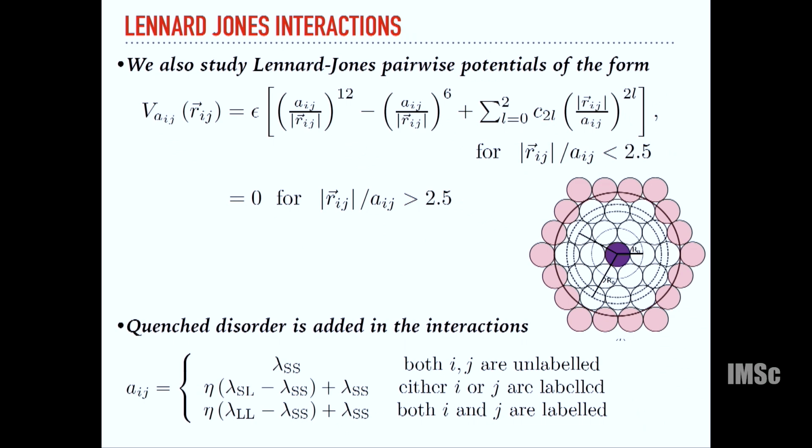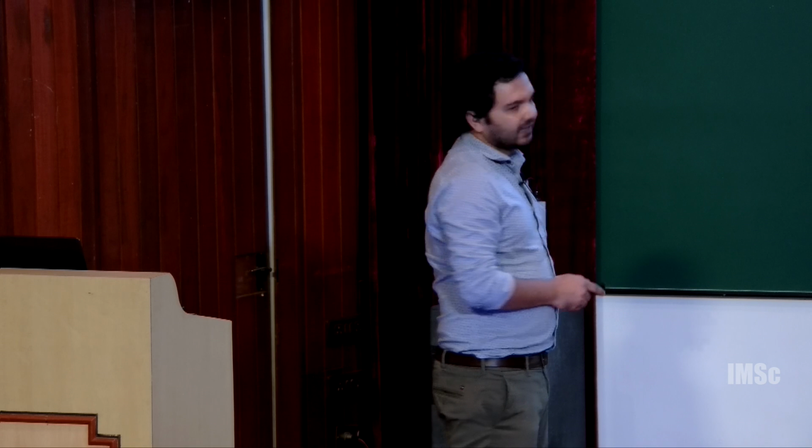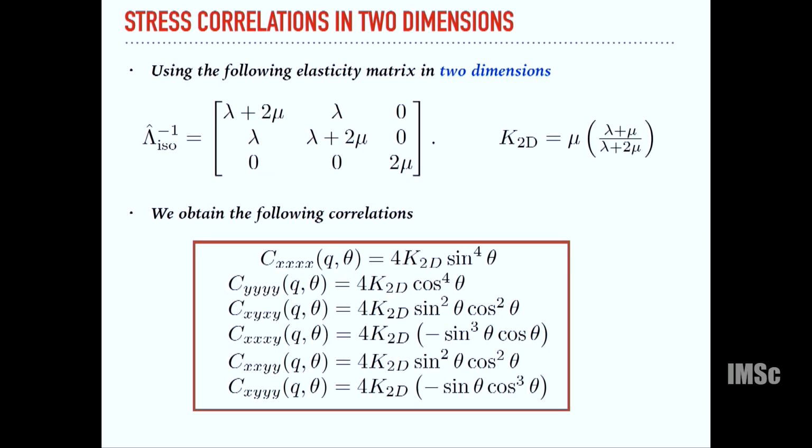Yes. And if you were to write it in a tensorial notation, then you wouldn't have this confusion. Is that correct? Absolutely. In fact, what I have written down here is the Lamé coefficients for isotropic elasticity. If I was to look at, for example, orthotropic elasticity or some locally broken symmetry elasticity, I would get off-diagonal components here. But this is isotropic elasticity. That's a very good question. If I added these terms, I would get deviations from this behavior. This is the isotropic case.